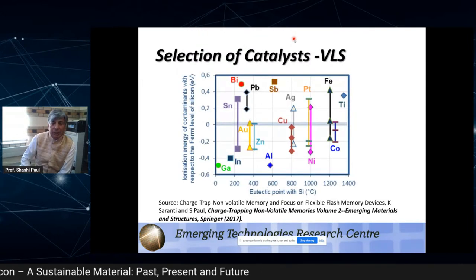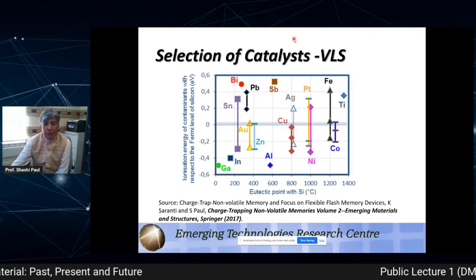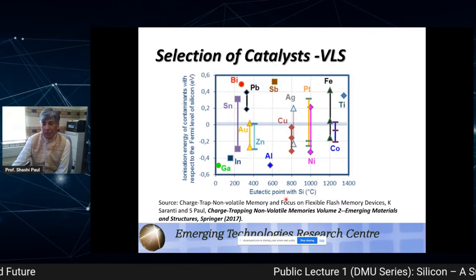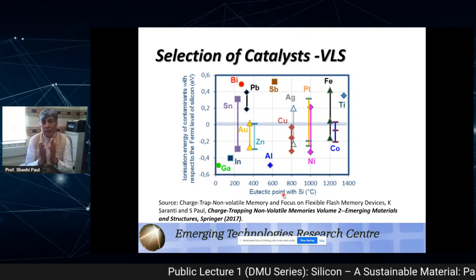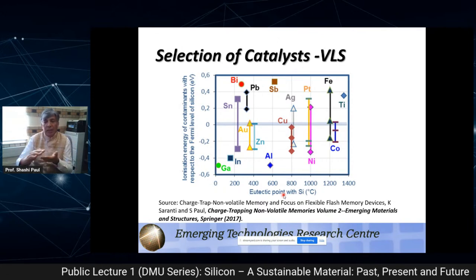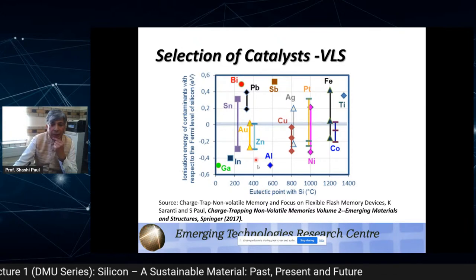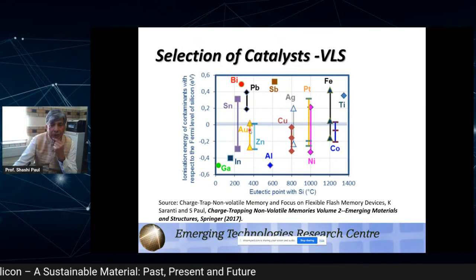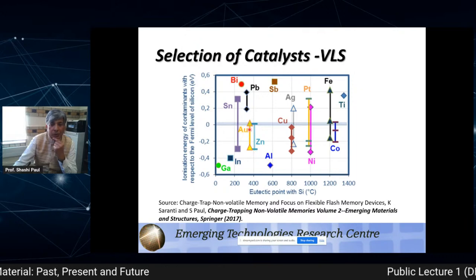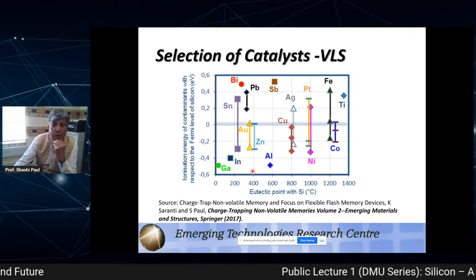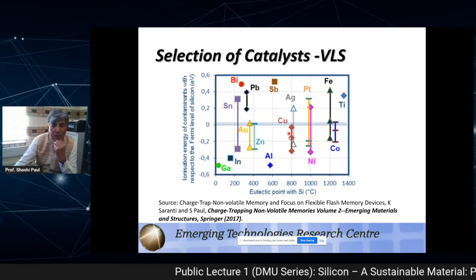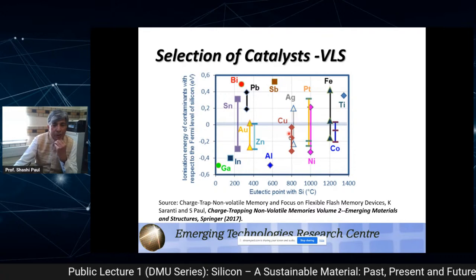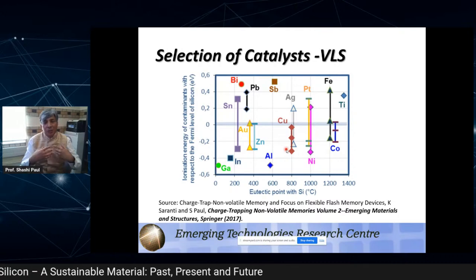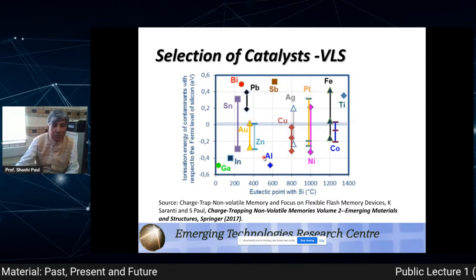The selection criterion for this process is something we call the eutectic point, basically the temperature between the metal you are going to use and silicon. For example, if you use gold, generally you will be able to make these structures at less than 400 degrees centigrade. However, if you use copper, it means around 800 degrees centigrade. If you want to use less temperature and dissipate less energy to the environment, you would probably go in this direction. So that is the VLS technique.